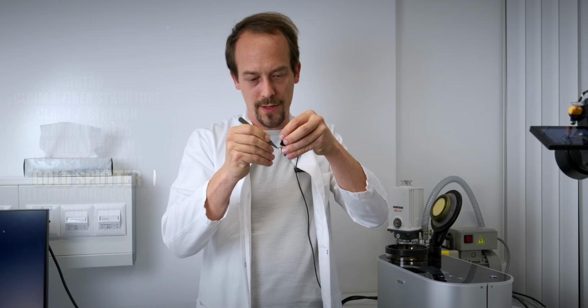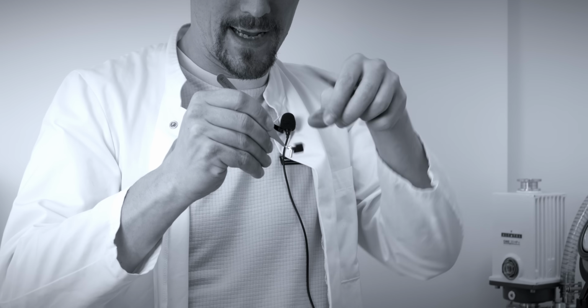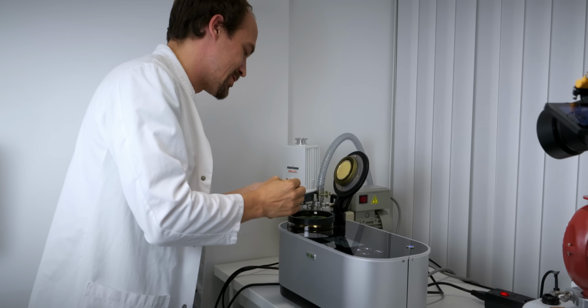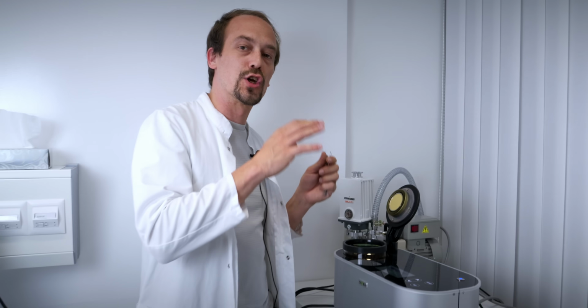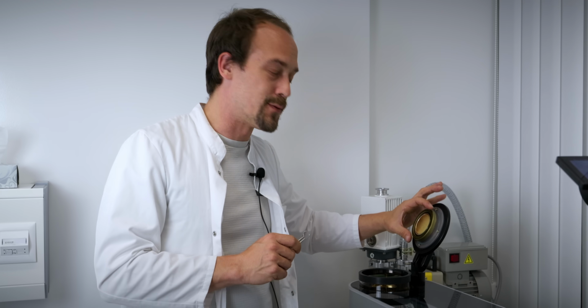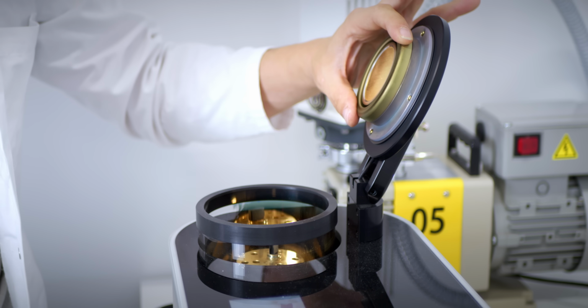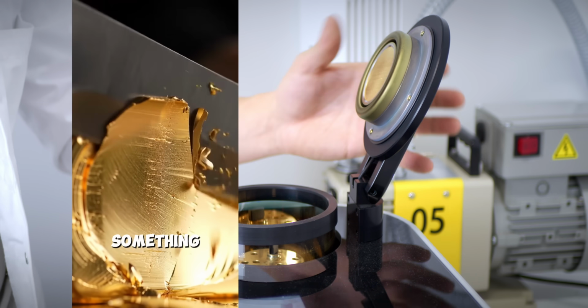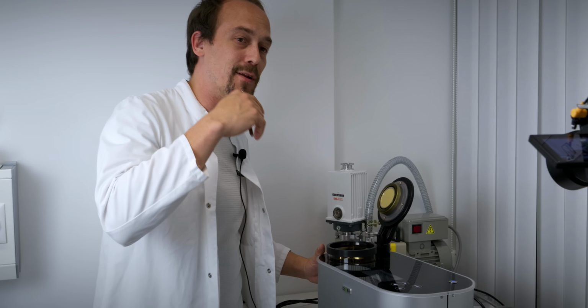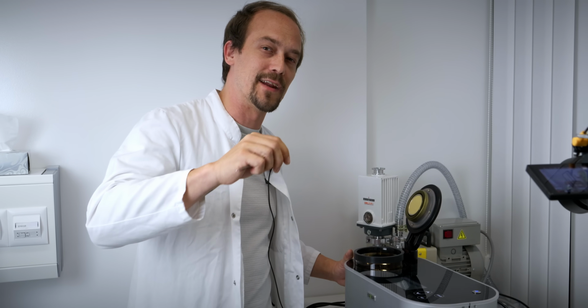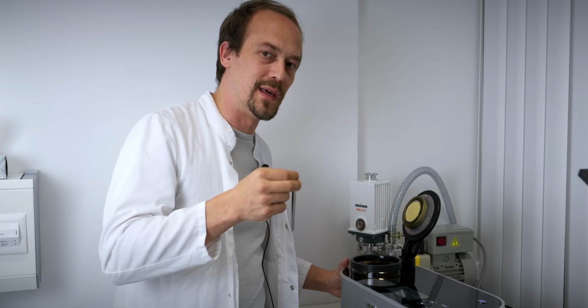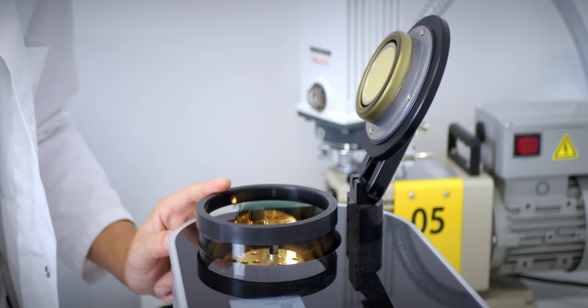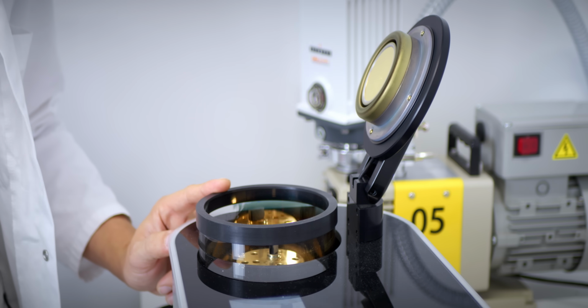We take our sample and put it on there simply with a little double-sided tape. And then we put it into this little machine. This machine is a gold sputter setup, a plasma sputterer. This little target up here is a pure gold disc. Yes, hundreds of dollars per gram gold. In order for our SEM to get a signal and read the surface of our sample, we're not looking at it optically, we're looking at it with an electron beam. We have to make our part conductive. And this machine adds a thin, nanometer thin gold layer onto our sample.